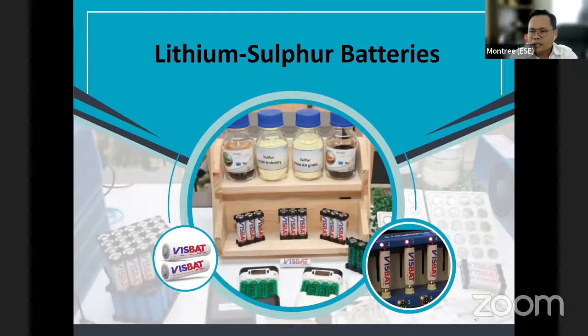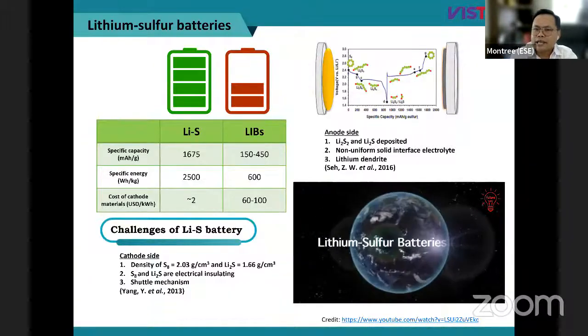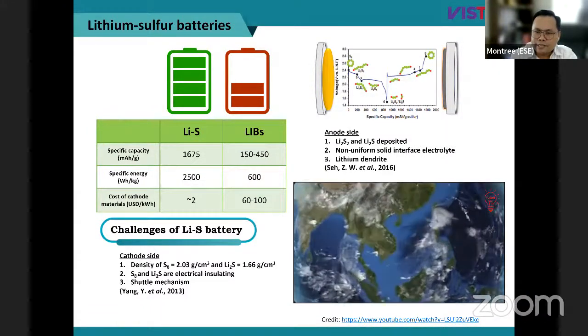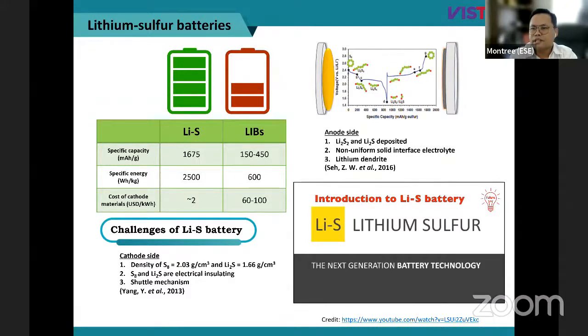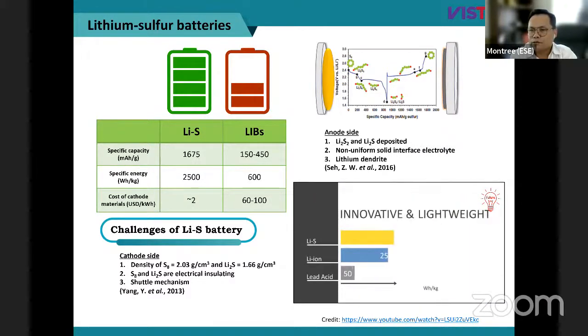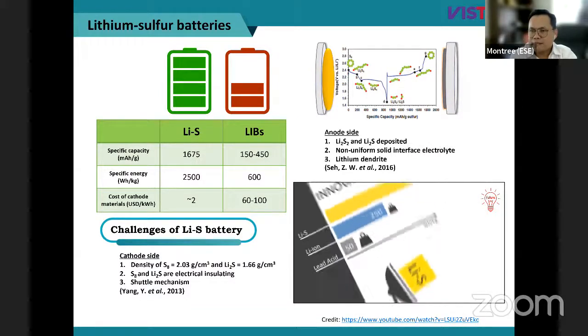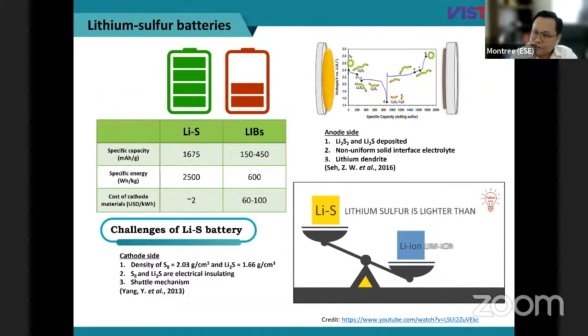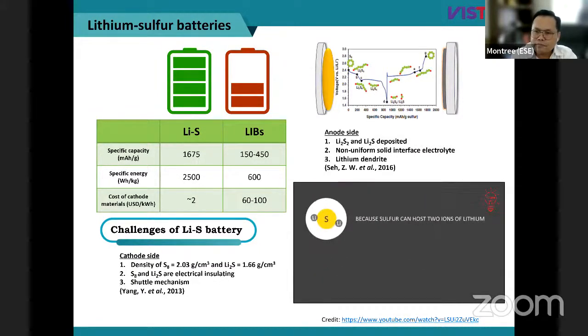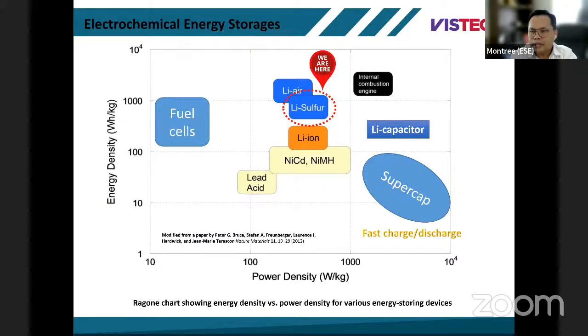You don't know yet, because there are some advantages and disadvantages, pros and cons, actually. It can provide you a high capacity, high energies, but the difficult thing is we need to deal with the lithium metal. So even when we put an all solid state electrolyte there, we still see some lithium dendrite. But sulfur is very cheap, so it's very good to do research in this field. And we hope that we can achieve it. Right now this is the progress we have. We still have issues at the lithium anode and safety concerns for the battery, but we can get really high energy.